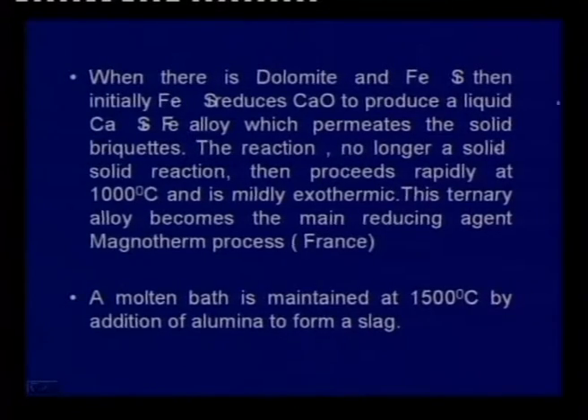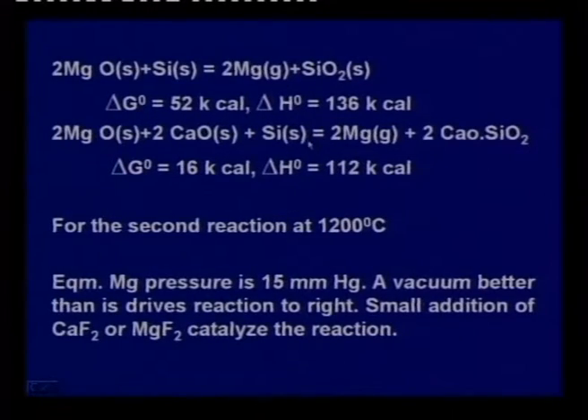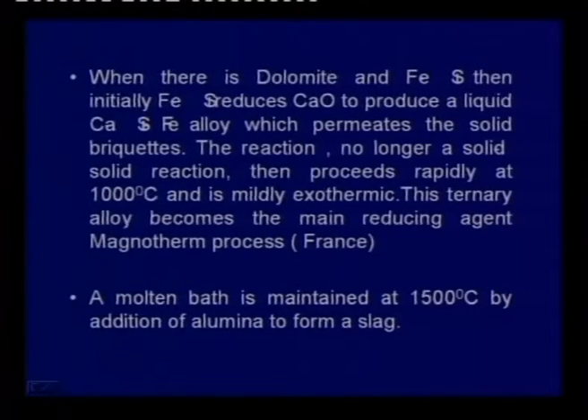We have talked about the mechanism, how it takes place. You might think it is a reaction between a solid and a solid, which is not true, because solid-solid reactions cannot be very efficient. How often do solid particles come in contact with each other? The surface of contact is very small, but essentially it is a reaction of a solid with a liquid. Initially the iron reduces CaO to produce liquid calcium, and a liquid calcium-iron alloy permeates the solid briquettes, and that is where the reaction takes place. It is not a solid reaction.